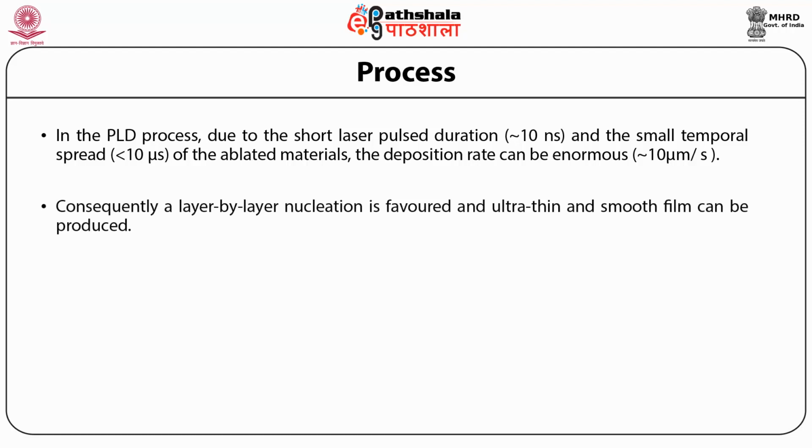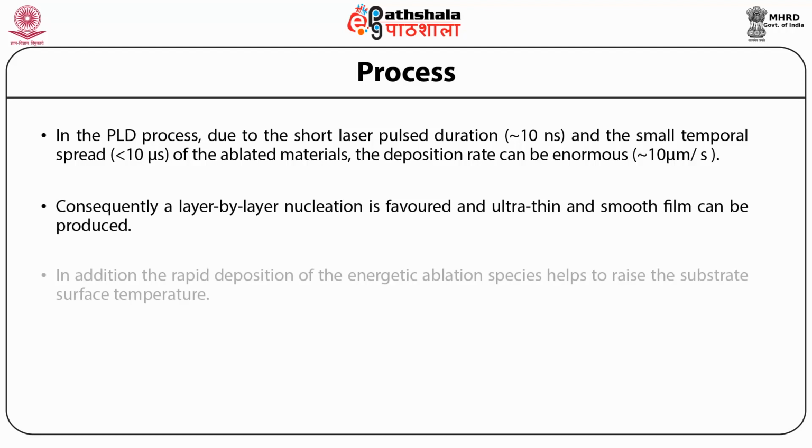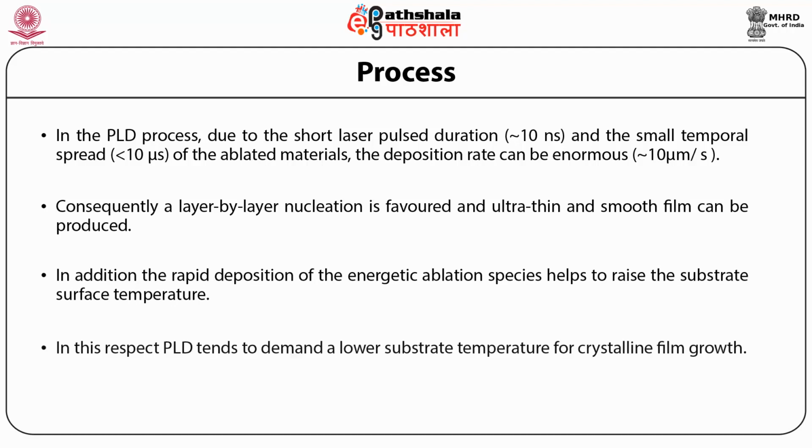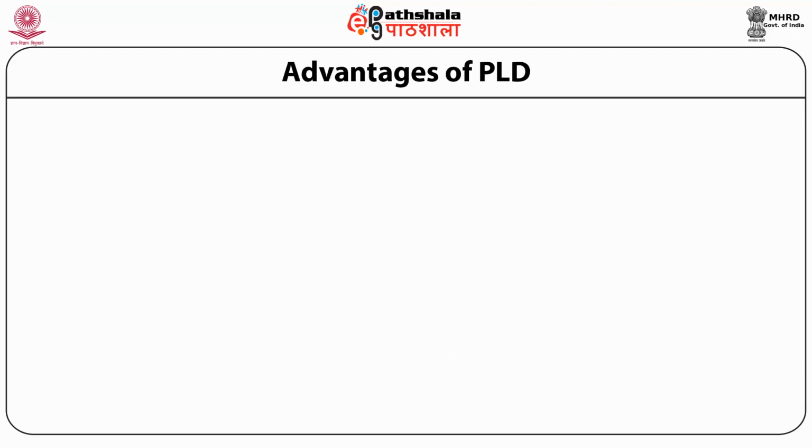Consequently, a layer by layer nucleation is favored and ultra thin and smooth film can be produced. In addition, the rapid deposition of the energetic ablation species helps to raise the substrate surface temperature. In this respect, PLD tends to demand a lower substrate temperature for crystalline film growth.